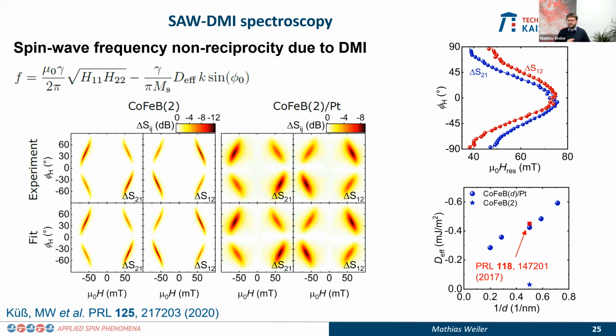So indeed, when we actually do these experiments and we take the spin wave non-reciprocity due to the Dzyaloshinskii-Moriya interaction into account, you can see here our experimental data. You see here is the cobalt iron boron that I showed you previously, and you can see there is an amplitude non-reciprocity. If we take some direction of the external magnetic field, then we compare this point to the same point for the opposite propagation direction of the surface acoustic waves. There is a clear difference in amplitude, but there is no difference in the resonance field.